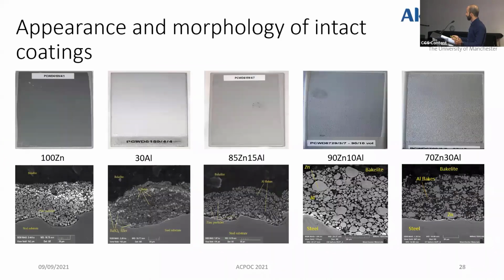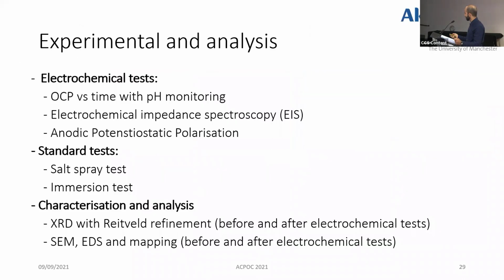As for the appearance and morphology of the intact coatings, as you can see for the physical appearance, the higher the zinc, the darker the appearance, and vice versa for the aluminum content. And in the SEM morphology, you can see the 100 zinc is fully loaded with zinc particles. For 30 aluminum, you can see that the aluminum flakes stack over each other like sheets. And then for the rest of the zinc and aluminum coatings, you can see that aluminum flakes are dispersed evenly between the zinc particles. The smaller the aluminum flakes, the smaller the gaps that are filled, especially in this one here, where you can see smaller flakes just in the vacancies between the zinc particles.